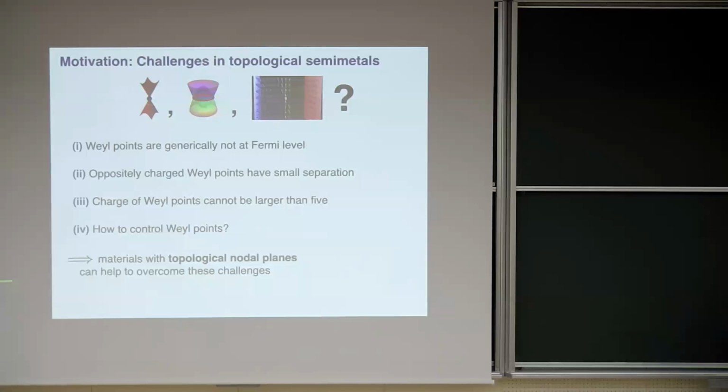Someone needs to have some fine-tuning, or for the material one needs to have the right doping to put this Weyl point at the Fermi level, such that it dominates the transport properties, which would be important for an application. Another problem is that often one has these oppositely charged Weyl points very close together in the Brillouin zone. So then the effects, these topological effects that one would like to see in the transport, would be washed out